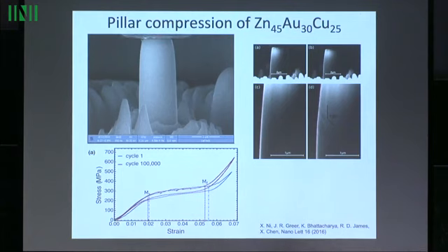And one thing that's quite unusual about this, at these scales, an ordinary martensitic material would show a big fat band of martensite across the middle. And here, there's microstructure at a much finer scale than even micron scale.